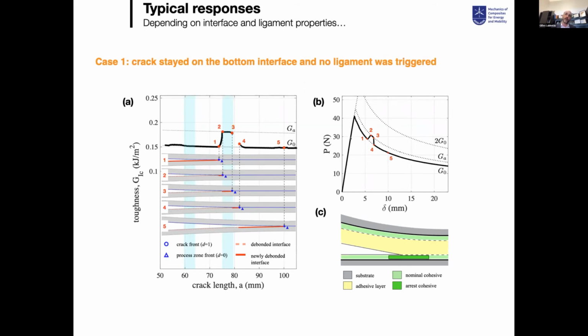So you expect to see a load displacement curve that is like this one, a P delta curve. So for those who already did some DCB delamination, you recognize a classical DCB. The only thing that you can see is that when you go across the local reinforcement here with stronger properties, locally you have an improvement of the delamination curve, and you switch from the low toughness to the high toughness, but you don't get more than the performance of your superior surface treatment.